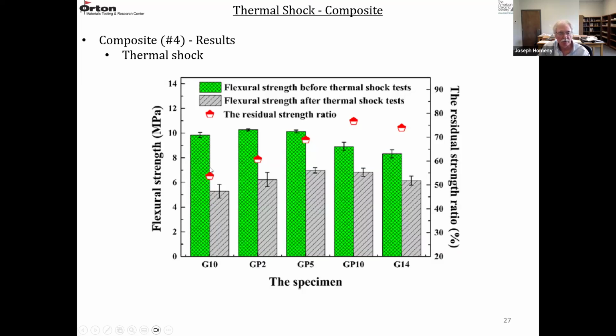So the composite without any pellets, the strength was comparable to GP2, GP5, and GP10, but the damage after thermal shock was greater, so it had a lower strength after thermal shock. And you can see as you increase the pellet concentration, the residual strength goes up, the strength after thermal shocking goes up, and it reaches a maximum somewhere between GP5 and GP10, and then it starts falling off again a little bit. But all of the samples with pellets had a higher strength after thermal shock than the sample without the pellets, and they all had a higher residual strength ratio. So the addition of pellets certainly improved the thermal shock behavior.